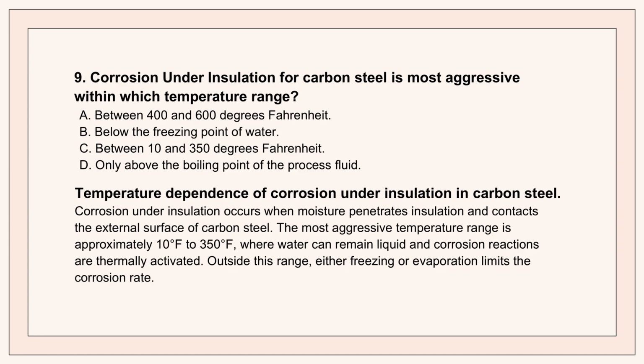Let's start with the classic one, corrosion under insulation, or CUI. Notoriously difficult to detect. We know you need moisture, but temperature is the accelerator. What's the most aggressive temperature range for CUI? It's between 10 and 350 degrees Fahrenheit. That's a huge range. It is. So why is that specific range the corrosion Goldilocks zone?